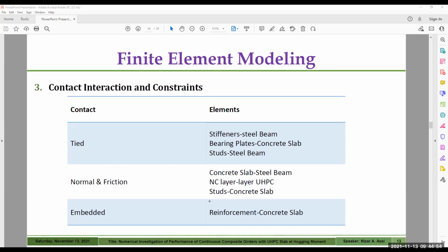For the interaction between different materials and different bonds in the model, we have different contacts as shown in this table. Tied, or perfect bond, was used to model the connection between the stiffeners and the steel beam, the bearing plates and the concrete beam, and the shear studs or shear connectors and the steel beam. While normal and shear friction was used to model the interaction between the concrete slab and the steel beam, the layers of normal concrete and ultra high performance concrete, and the shear studs and the concrete slab. The steel reinforcement within the concrete slab was modeled as embedded elements inside the concrete slab.